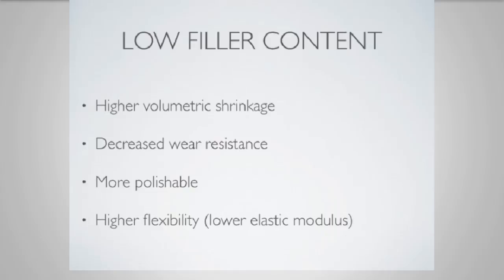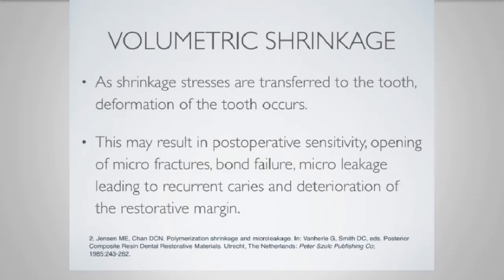So what's the problem with volumetric shrinkage? Because we don't like the idea of the shrinkage factor that's happening on the teeth and what it's doing to the teeth. What exactly is happening? As the shrinkage stresses are transferred to the tooth, deformation of the tooth occurs. And in doing so, this may result in postoperative sensitivity, opening of microfractures, bond failure, microleakage, and it could lead to recurrent caries and deterioration of the restorative margin. Now, it's surmised that the lower elastic modulus, the lower modulus means it's a higher flexibility, compensates for the higher shrinkage.